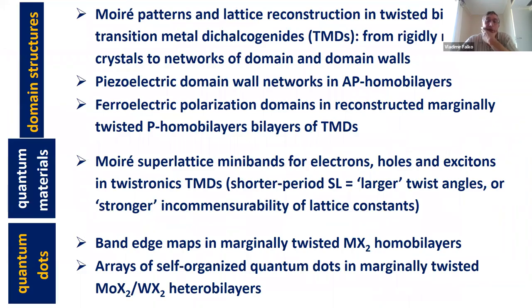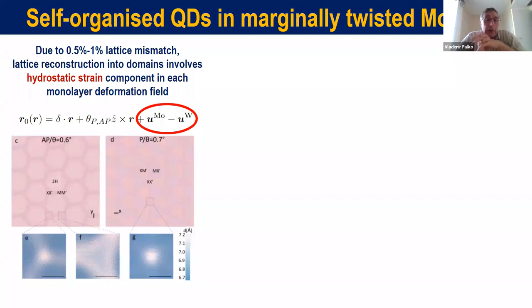So I now jump into the last part of what I would like to describe, and this is about the hetero bilayers, which contain the same dichalcogen materials in both monolayers. And the reason why those are interesting is because they have pretty close lattice constants, so that those allow for a strong lattice reconstruction of slightly different type as compared to what happens in twisted homobilayers. In twisted homobilayers, the strain has to compensate the rotation of one layer with respect to another, and therefore, in that case, strain was dominantly shear. And when we need to compensate the difference in the lattice constants, then slightly different things happen.